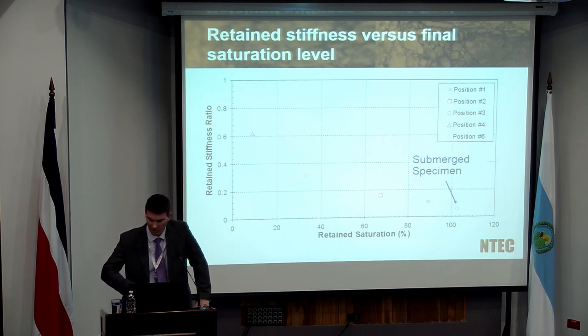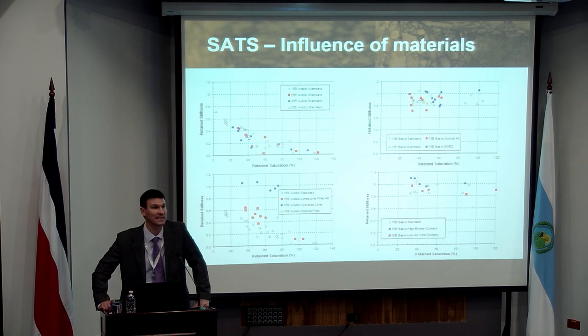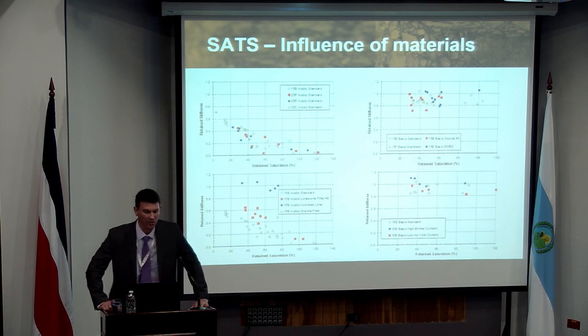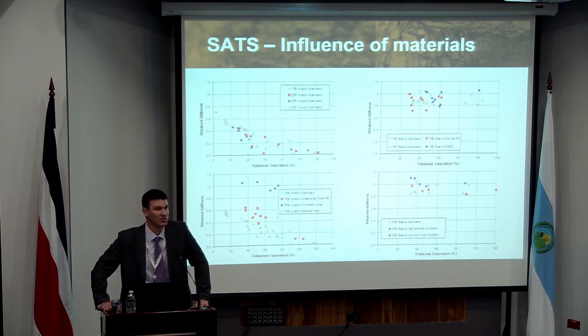And that's extremely useful if we start looking at big data sets. Because now I can see we're not going to get one result, we're going to get a whole range of different results. And in potential links to field performance, we can start to relate the saturation levels to what we would experience in the field. And so the top two diagrams, the one on the left is using an igneous rock, some kind of acidic granite type aggregate, and four different types of binder.